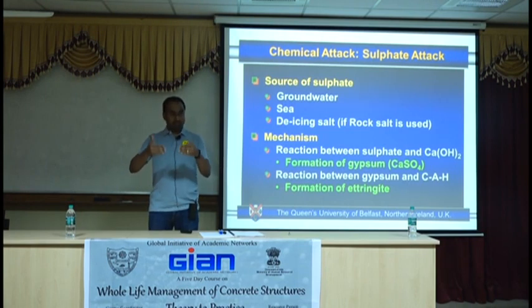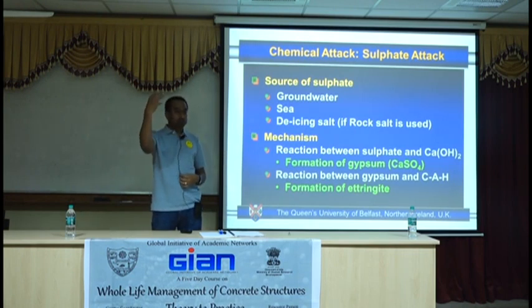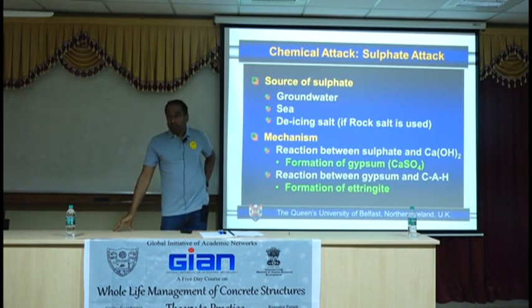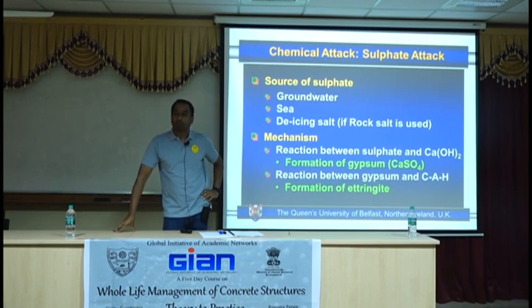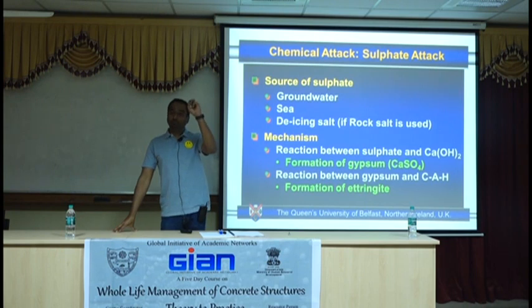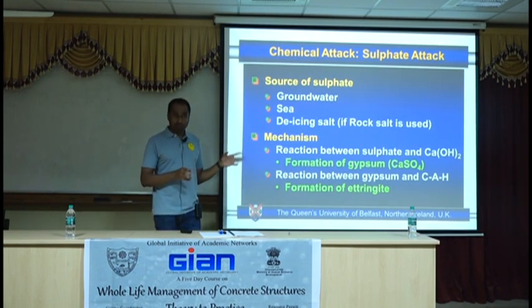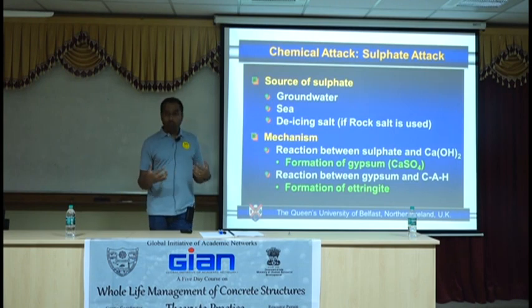It's a very slow, steady process. If you look at a concrete and you're seeing a lot of aggregates projecting out — unless it's a design feature — expect that there's something attacking the cement. You will see a lot of dusting as well. Quite often the dusting might be washed away if it's in a pipe; all you see is aggregates popping and falling out. It doesn't mean conclusively that that's sulfate attack — it could be freeze-thaw attack, it could be salt efflorescence — but sulfate is one of the possible reasons.